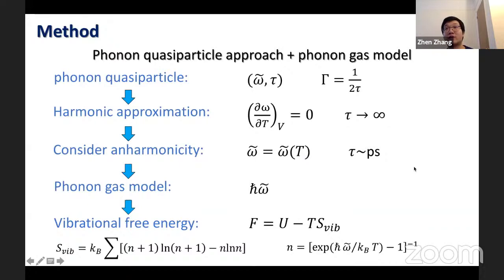Phonon is a kind of quasi-particle. It can be described by two parameters, the frequency omega and the lifetime tau, or the line width gamma. Gamma equals 1/2 tau. For harmonic approximation, omega does not depend on temperature. Phonons do not scatter with each other. Thus, the phonon lifetime is infinite.